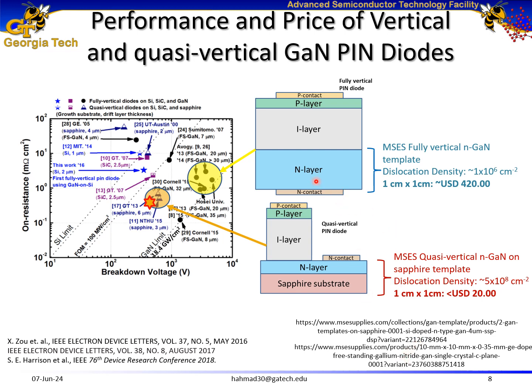Typically, there are two kinds of pin diodes. The fully vertical pin diodes, which are grown on top of bulk gallium nitride templates, and the quasi-vertical gallium nitride pin diodes, which are grown on foreign substrates. In terms of performance, the fully vertical gallium nitride pin diodes have much higher performance as compared to the quasi-vertical pin diodes. However, the fully vertical pin diodes are more than 20 times more costly as compared to the quasi-vertical pin diodes. And we know that cost is a major factor for high volume production. So this is the major motivation for me to pursue quasi-vertical gallium nitride based pin diodes.